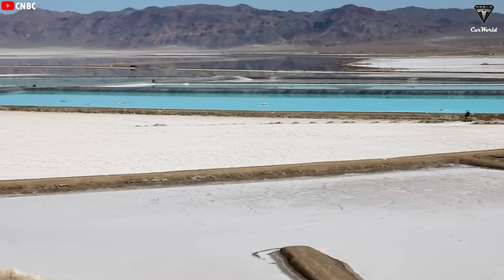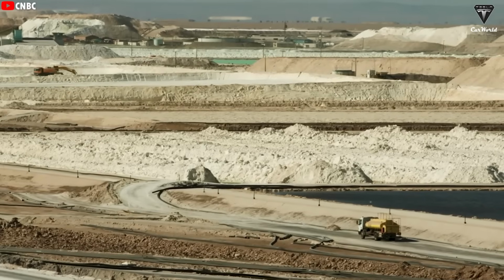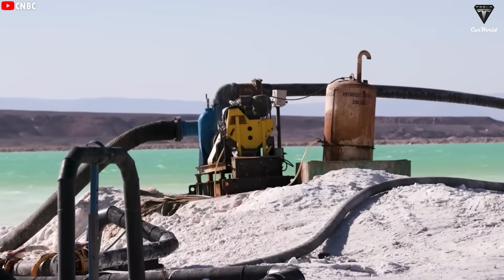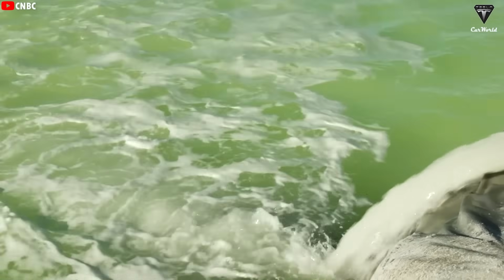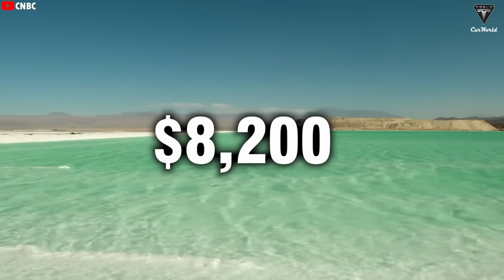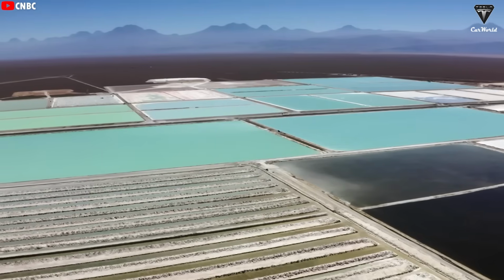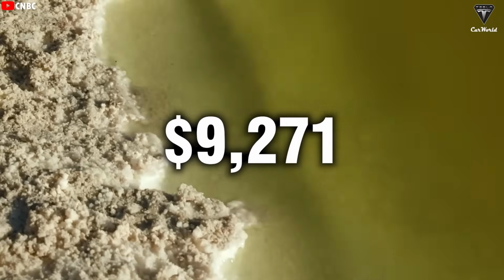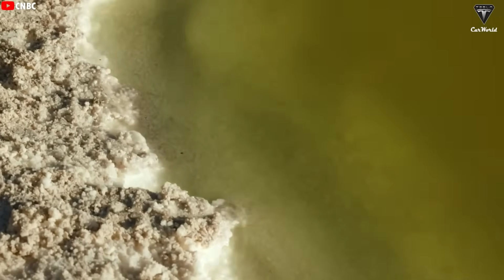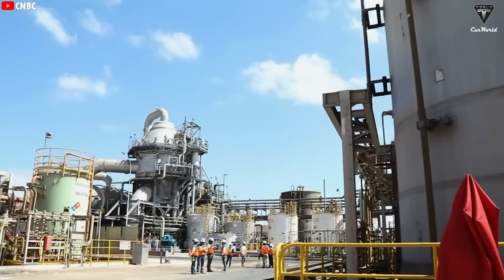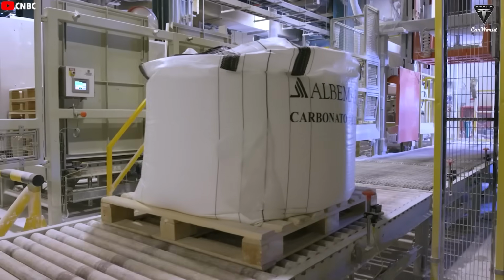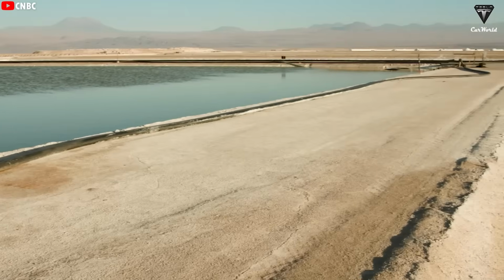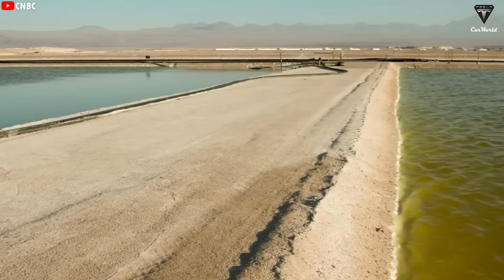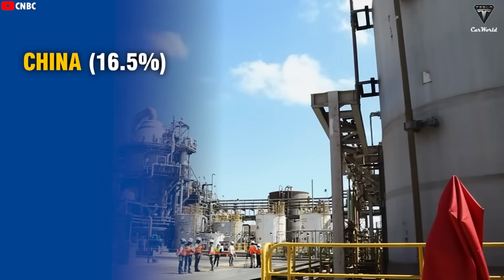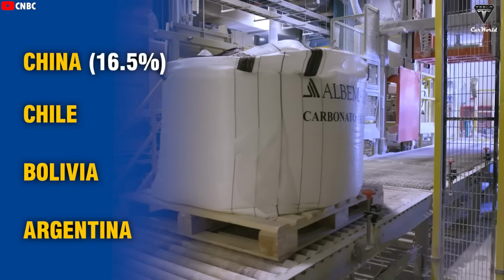Lithium prices have fluctuated sharply over the past 2 years, sometimes dropping but often spiking dramatically. As Elon Musk has pointed out, lithium prices have surged by as much as 500%. In 2024, the average price of lithium carbonate was about $8,200 per ton, and by February this year, it had risen to $9,271 per ton. This is due to global reserves of only about 89 million tons, nearly 18 times less abundant than aluminum. The situation is worsened by the geographic concentration of lithium. Most reserves are found in just 4 countries, with China holding about 16.5%, and the rest primarily in the lithium triangle of Chile, Bolivia, and Argentina.